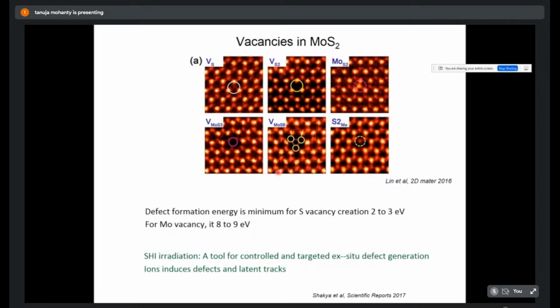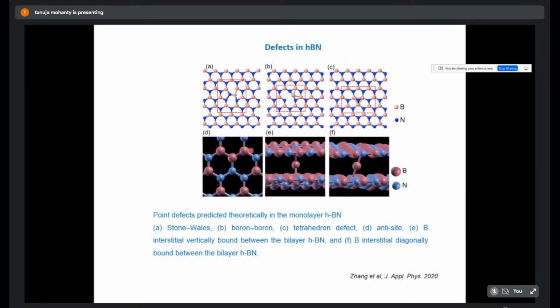Then I will tell you next about defects in hBN, that is hexagonal boron nitride. Boron nitride, as we just saw, has a band gap of 6 eV. So what are the defects? This is a similar kind of Stone-Wales defect as you have seen one slide back, where it is not hexagonal, it has 7 bonds, and somewhere it has just 5 bonds. So those are the Stone-Wales defects.